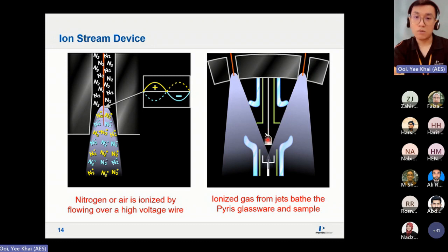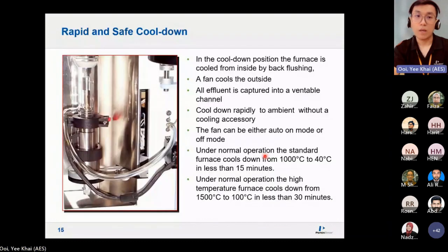Remember, this is your sample pan. Your sample is going to be here. Before it raises up, this ionized nitrogen will purge all your glassware and neutralize all the static charges. And then when you raise all this in a sealed environment, the pan will still be free hanging, without touching the side of the furnace. So this is another thing that protects your data integrity. And we have a rapid and safe cool down that takes from 1000 to 40 degrees C in less than 15 minutes without any water chiller required.